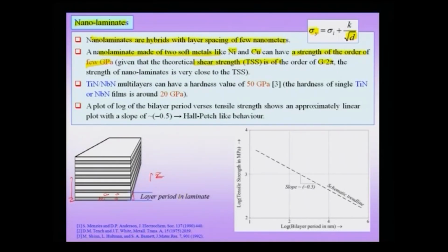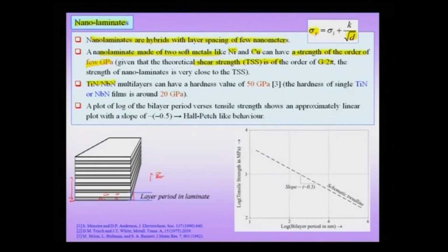This is a very beautiful and strange effect. That means that we are getting very high strengths in these nano laminates, while each one of those components, nickel and copper, actually are very soft metals. In titanium nitride, niobium nitride multilayers, that means one layer is titanium nitride, the other layer is niobium nitride, we can have a hardness value approaching that of about 50 GPa.